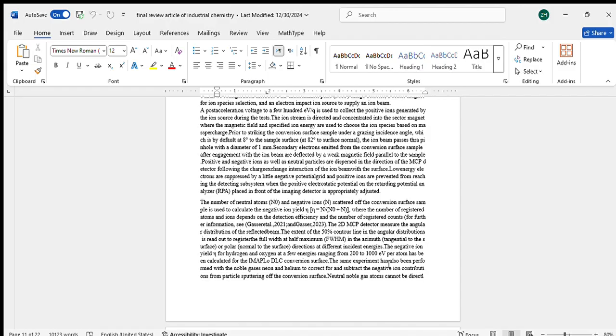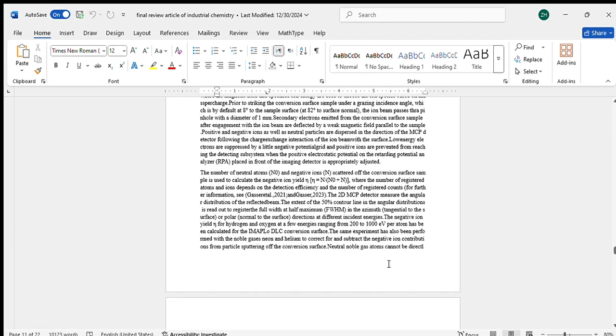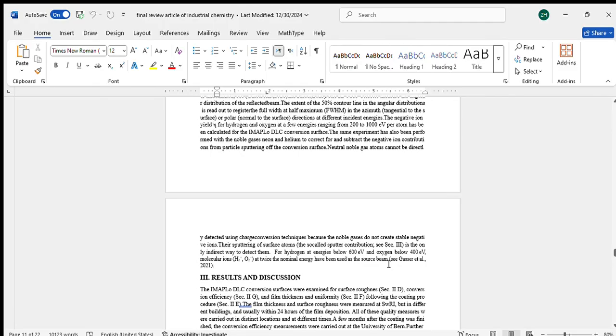The same experiment has also been performed with the noble gases neon and helium to correct for and subtract the negative ion contributions. For particles sputtering off the conversion surface, neutral noble gas atoms cannot be detected using the charge conversion technique because the noble gases do not create stable negative ions. Their sputtering of the surface atoms, the sputter contributions, is an indirect way to detect them. For hydrogen at energy 600 electron volt and oxygen below 400 electron volt, molecule ions H2 positive and O2 positive at twice the nominal energies have been used at the source beam.